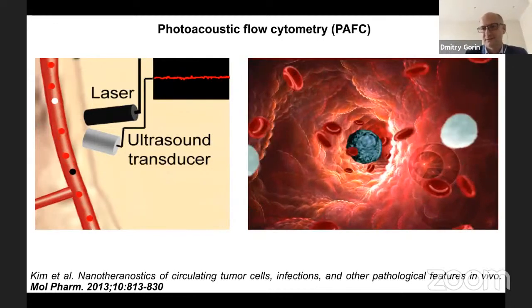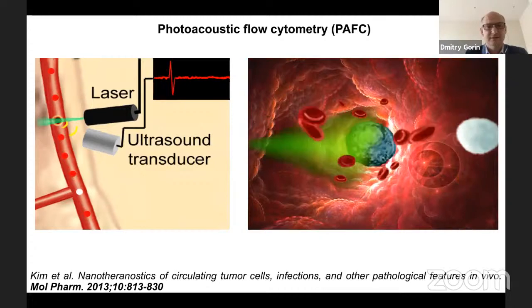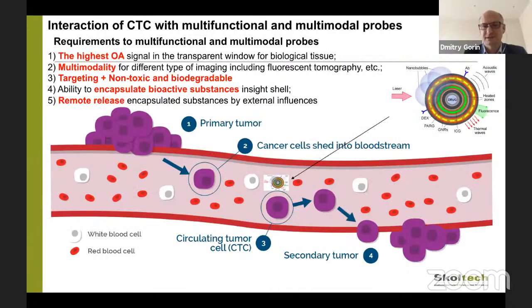to destroy these cells. But unfortunately, most of these cells don't have any chromophores like melanin, and therefore we need to prepare a contrast agent that gives us an optoacoustic signal, and here you see the requirements for this probe. The first, we need to have the highest optoacoustic signal. The second, we need a second modality like fluorescence. Why? Because we need to verify our data.